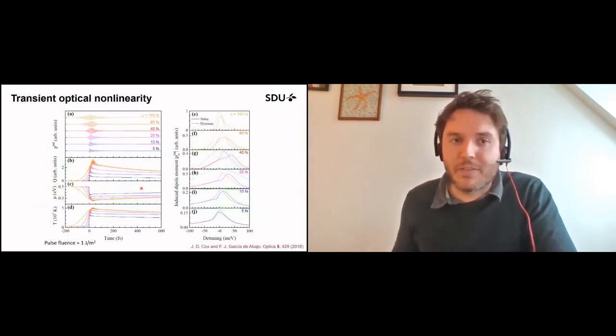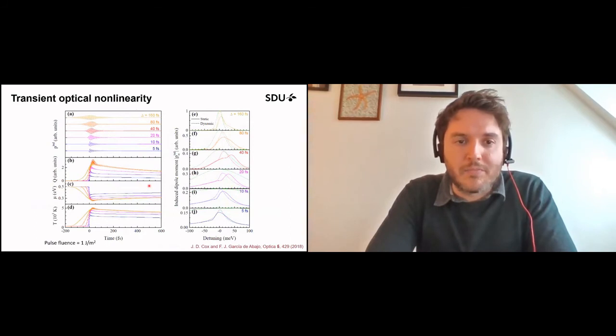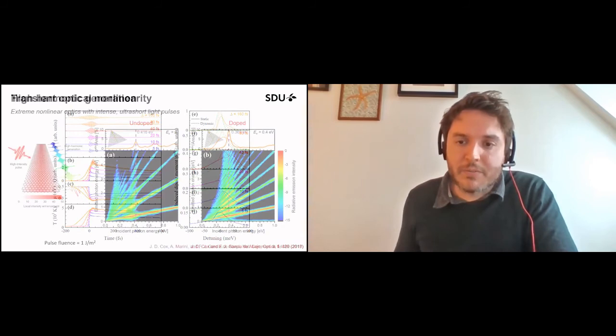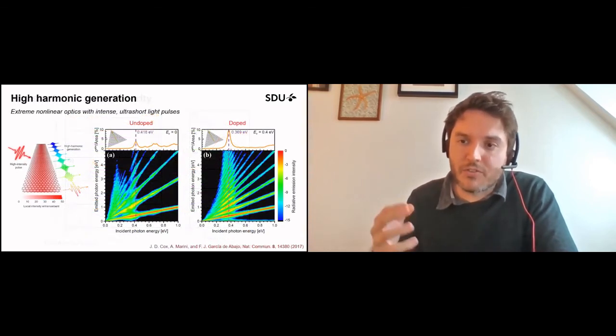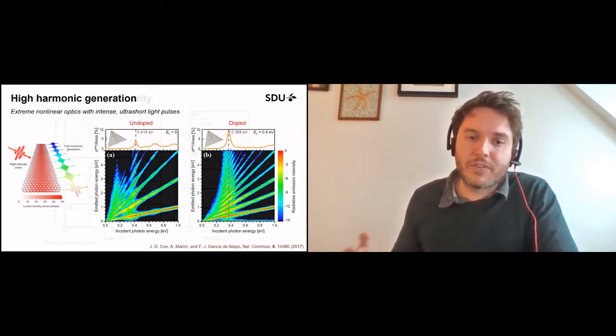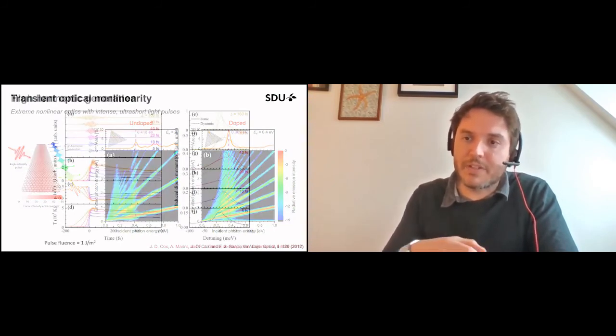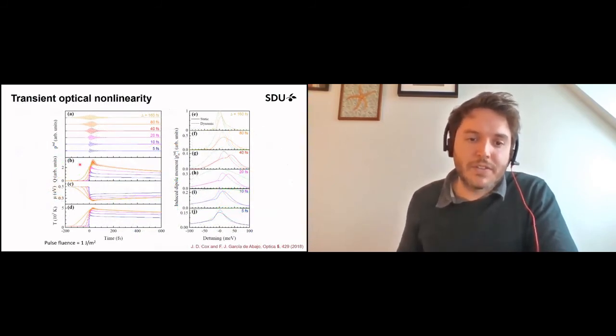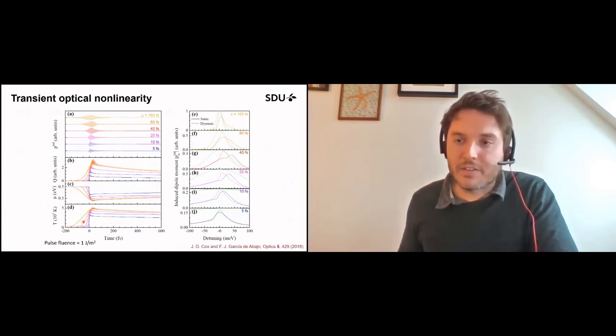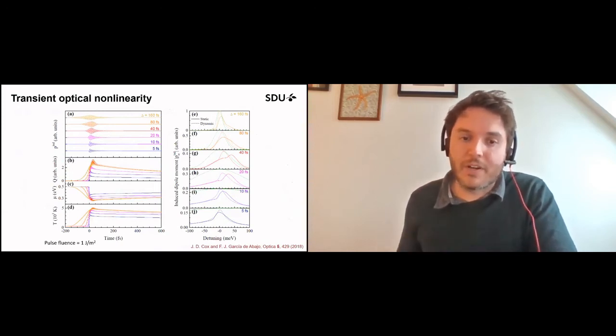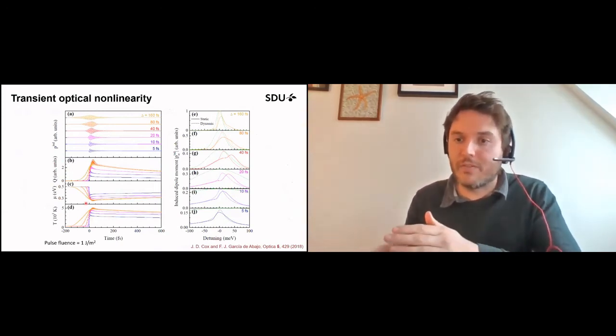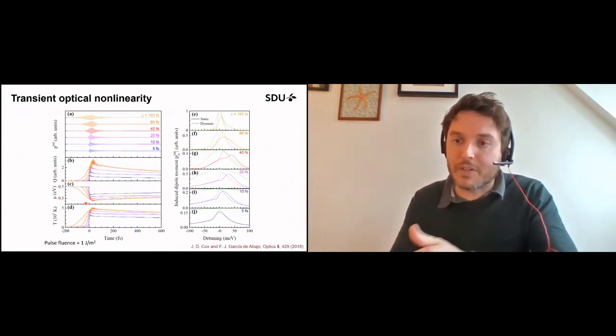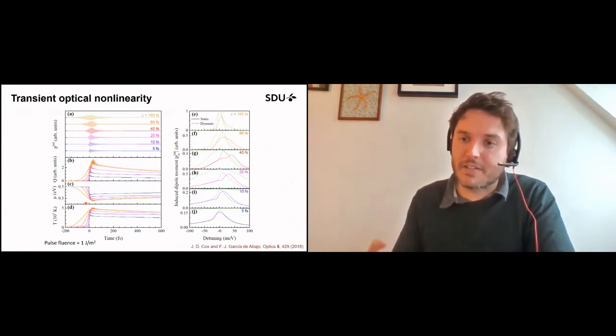So just to save on time, I think I'm running a little long. I'll just mention briefly that this process is an extreme nonlinear optical process. So it means that you really strongly excite the graphene. It means you deliver a lot of energy to the graphene plasmon. It gets absorbed, and you can dramatically increase the temperature in the graphene island, just the temperature of the electrons, which in turn is sort of like optically doping your graphene nano island. So rather than electrically gating the system, you can optically dope the system, because again, it's very susceptible to changes in its electronic structure.